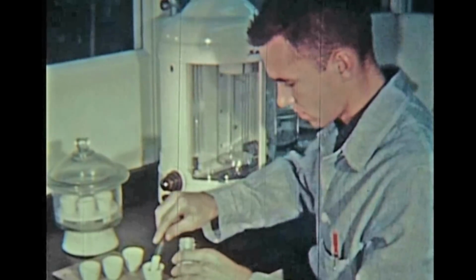Further drying is done in these trays in an oven. The dried crystals are sifted to remove any oversized particles. Crystals are weighed and then stored in drums. These crystals are the basic material for reduction to metal. At this point, samples are taken and tests run for purity and size.